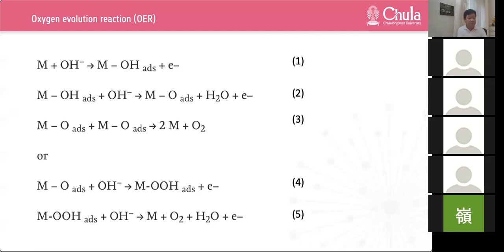Generally, precious metal oxides such as ruthenium oxide or iridium oxide are known to be highly active toward OER because of high electrical conductivity and low redox potential. However, these precious metal-based oxides are very costly and have only demonstrated limited ORR activity, insufficient for use as bifunctional catalysts for rechargeable metal air batteries. Conversely, much more cost-effective and strongly bifunctional transition metal oxide catalysts such as cobalt oxide and nickel cobalt oxide have shown high activity for both OER and ORR with electrochemical stability.